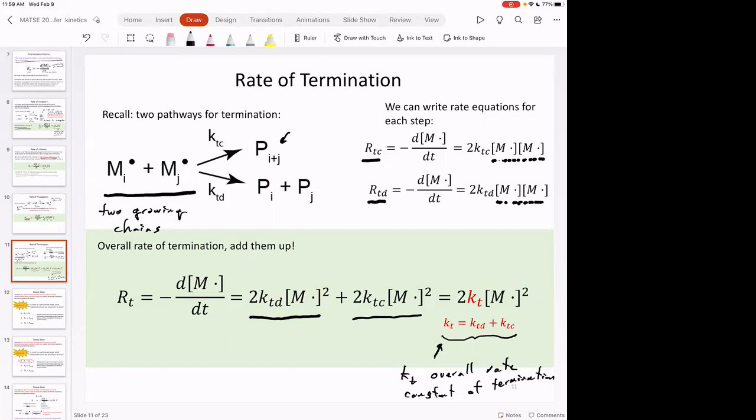Because what is the principle that we talked about where all chemical reactions happen at the same rate no matter what the molecular weight is? Principle of equal reactivity, right? And so this is a little bit of a simplified view, but because of the principle of equal reactivity, we just have to address the reactive species. We don't have to address the molecular weight dependence.